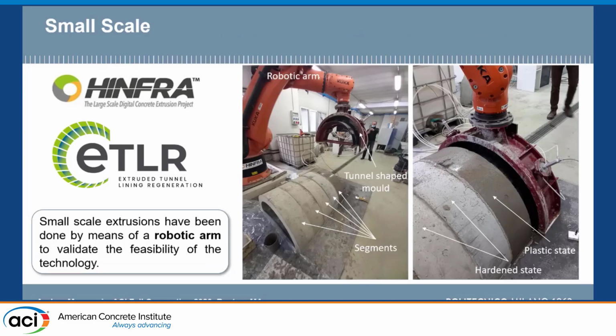To assess the feasibility of this methodology, we started from small scale testing, and this was made thanks to the use of a robotic arm that is commonly used for 3D concrete printing. In this case, a tunnel-shaped mold has been mounted on the nozzle in order to give the shape during the extrusion. As you can see, there are some similarities between this technology and 3D concrete printing, especially in the material requirements. As a matter of fact, the material must be buildable in order to start the slipping of the mold, so that the segment can sustain its own weight.